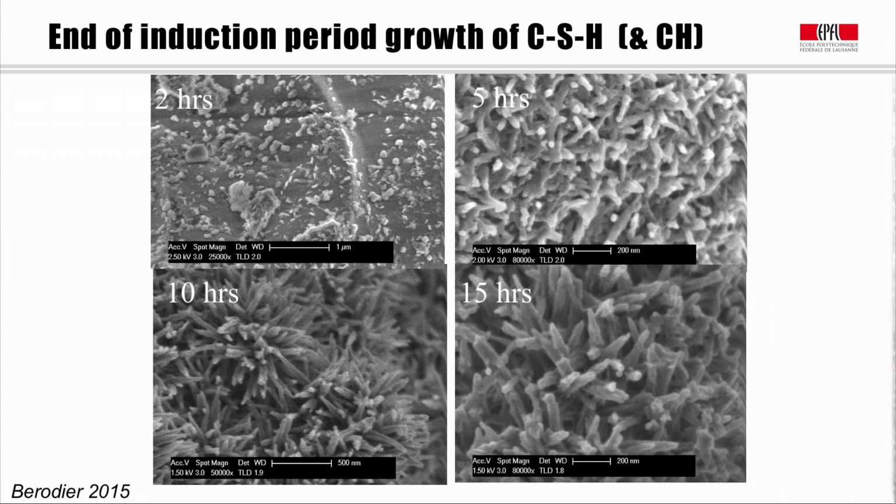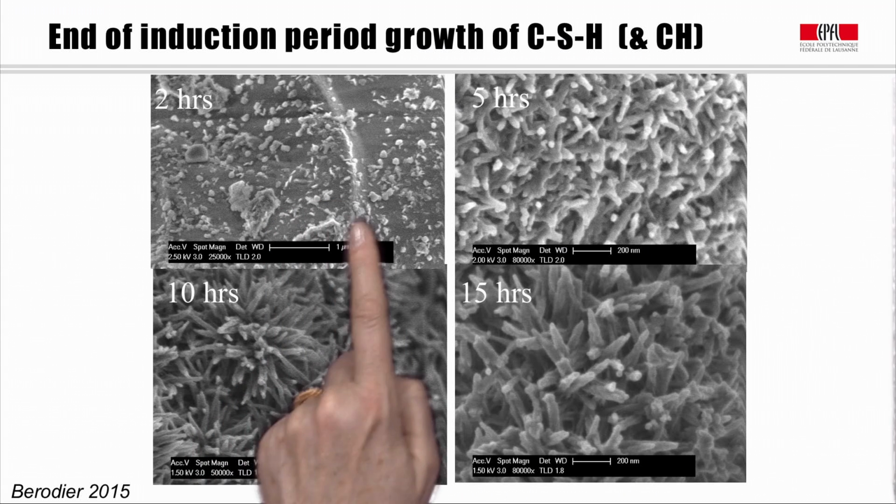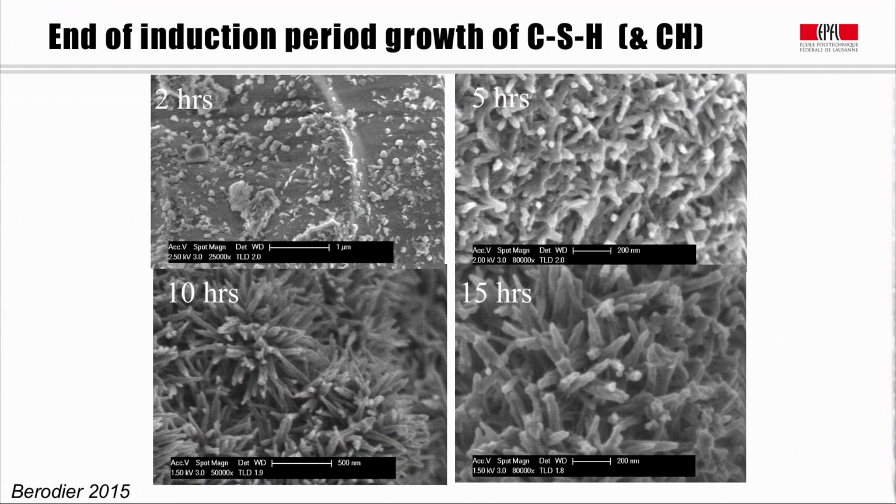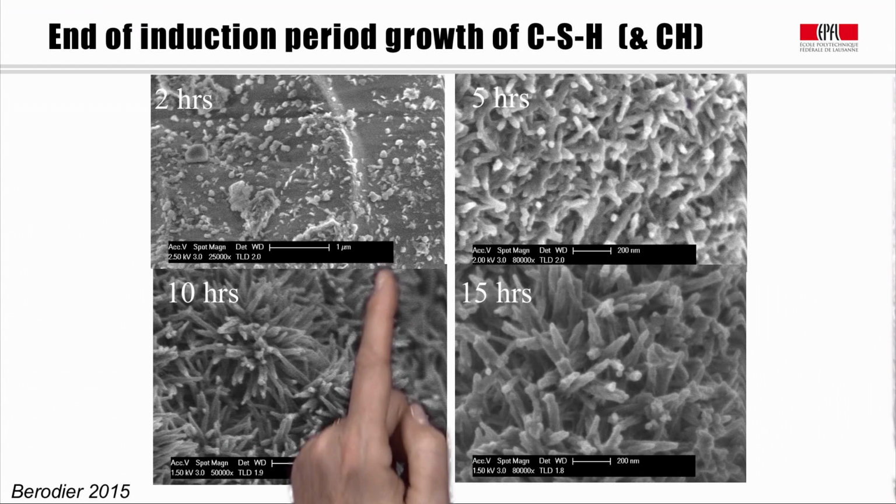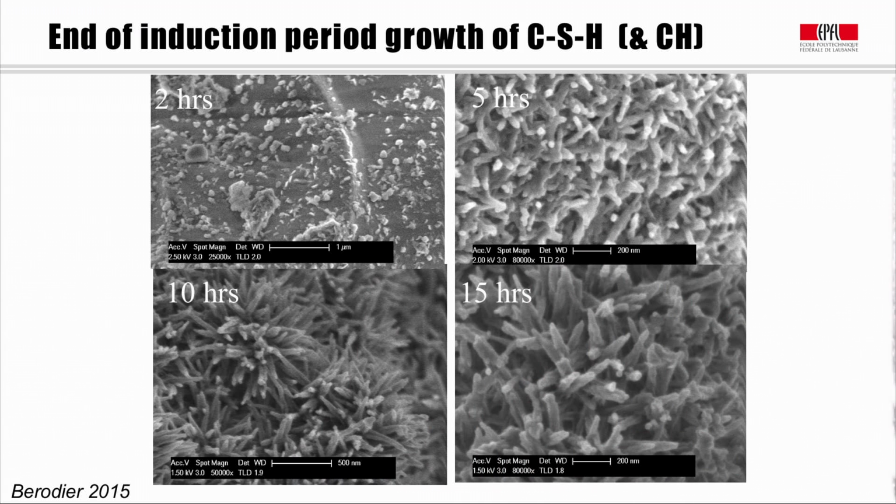So in terms of what's happening in acceleration, I think the situation is quite clear, that here we're looking at the nucleation and then the growth of CSH. So on these slides, we can quite see at about 2 hours, we can see these little tiny nuclei of the CSH which are forming, and then those nuclei grow over time. And as they grow over time, they grow in what we often call a kind of needle morphology, where it looks a little bit like a sea urchin.